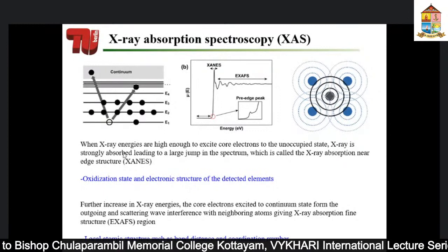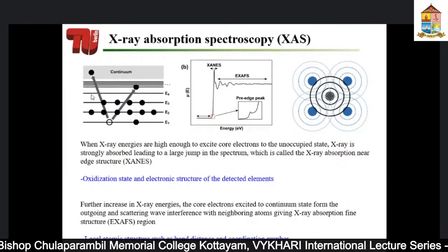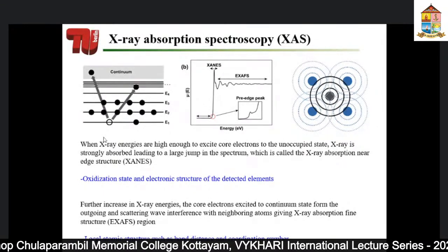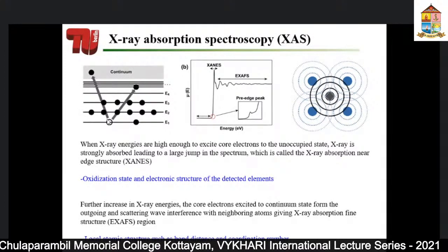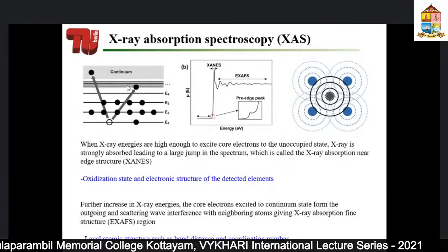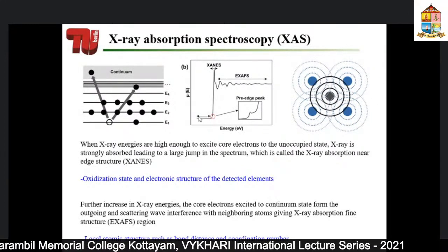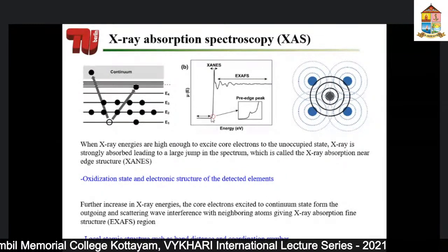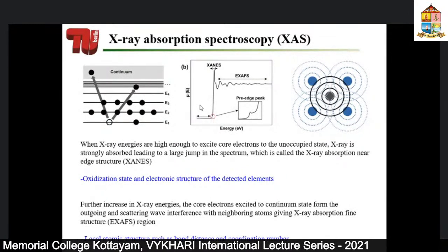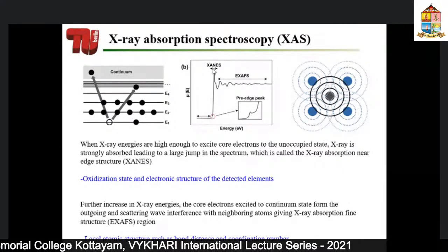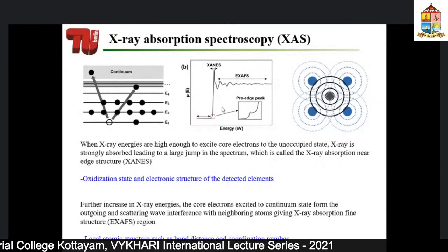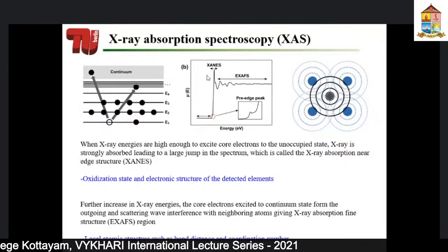So when your X-ray energies are enough to excite the core electron of the material to the unoccupied state, then you get a sudden jump in the spectrum, which is energy versus intensity, and you see an immediate jump. This portion would give you the oxidation state and the electronic structure of the elements.